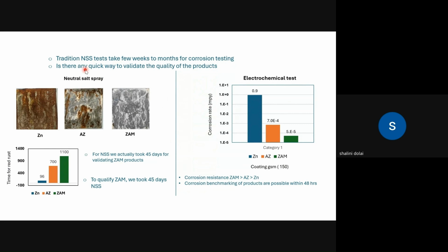So you can see we used the same techniques which I explained earlier. In a neutral salt spray, we kept all these three coatings. The zinc coating was corroding at a very high speed, whereas the zinc-aluminum-magnesium coating didn't show any signs of bleeding or red rust. But this test took 45 days for me to conclude, and the results were not very conclusive. Visually, we can tell this is better than this, but how to quantify it? Is it 5 times better, 10 times better?